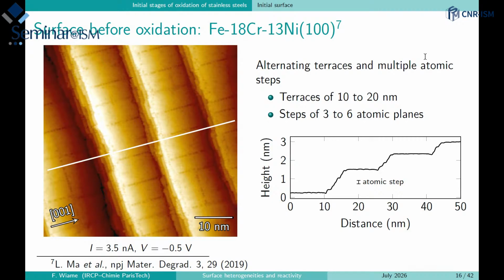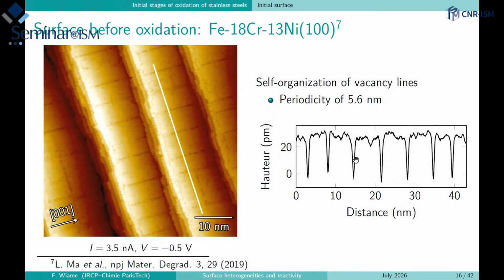If now we are looking at the structure of the surface, so for example, here the structure of the 304 surface, we can see on this profile that we have some alternating atomically flat terraces of about 10 to 20 nanometer, which are alternating with some steps of 3 to 6 atomic planes. And if we are looking at what's happening on the terraces, we can see that we have some vacancy lines, which are periodic, with a periodicity of about 5.6 nanometer, with a depth of about 20 picometer in height on these surfaces.